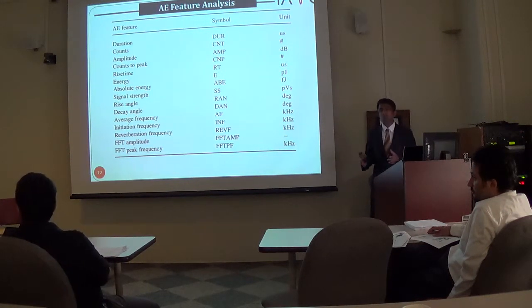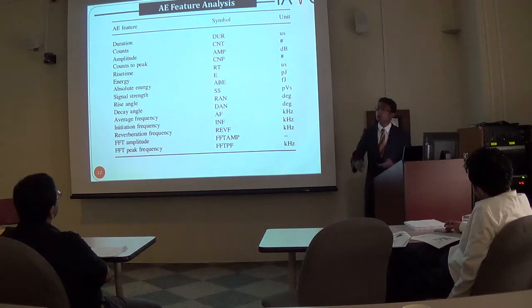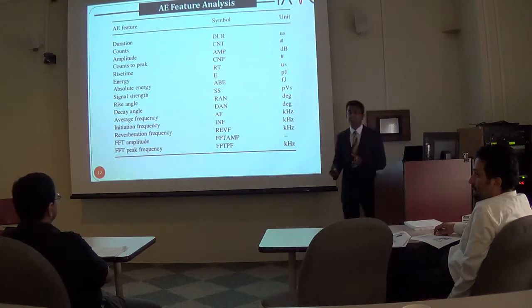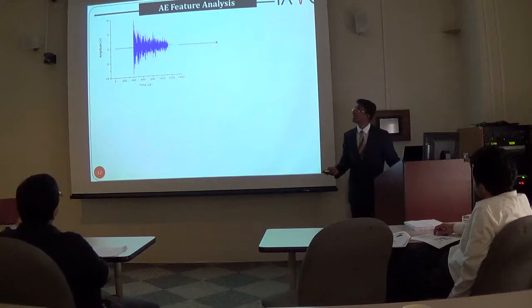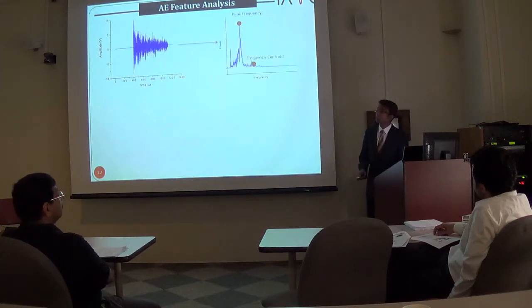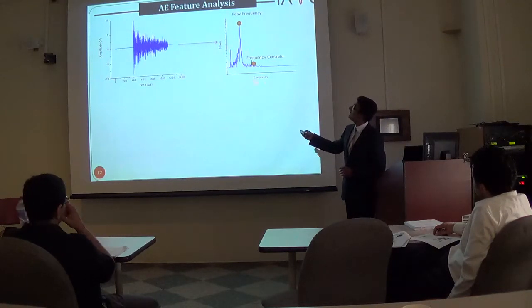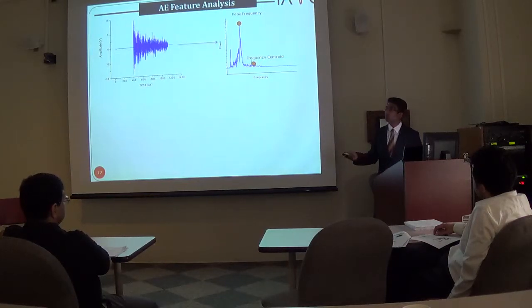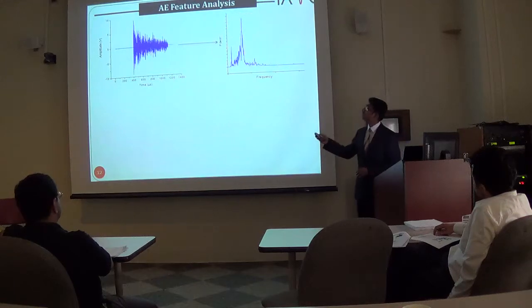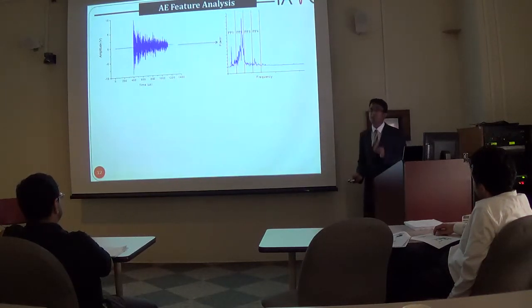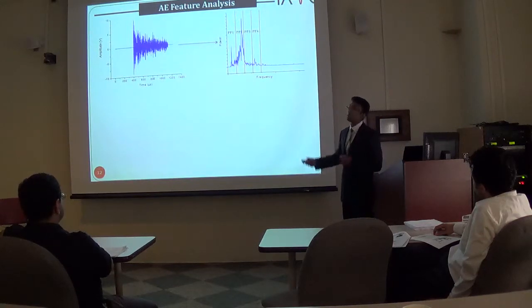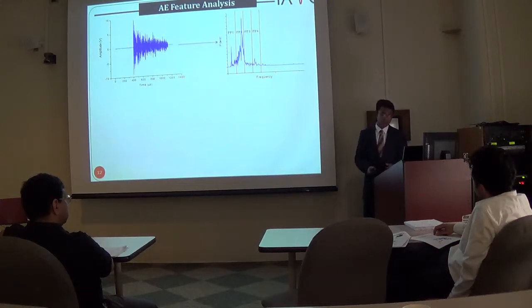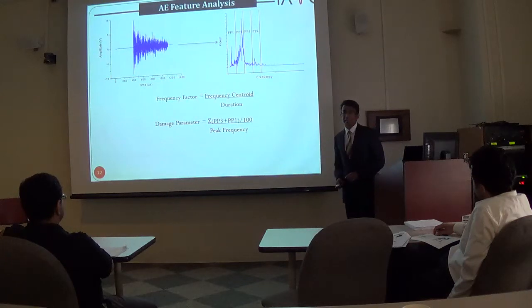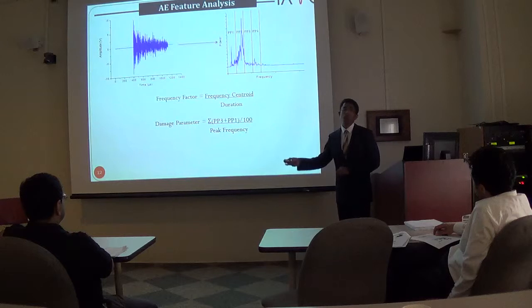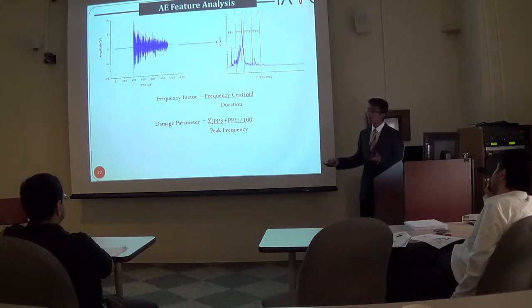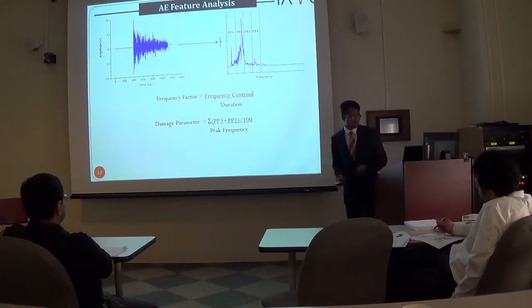However, in our research, I wanted to go a few steps further and develop both novel AE descriptors and also advanced AE feature descriptors that are reliable for damage detection. For that purpose, the AE waveforms extracted during the test were comprehensively analyzed and shifted to the frequency domain using FFT algorithms. In addition to picking up the peak frequency, other advanced frequency analysis was also performed to identify the frequency centroid. Further, the FFT spectra were dissected carefully into 4 specific spectral ranges, and the percentage of energy in each of these spectral ranges was then calculated and seen to be correlated with the applied loading conditions. Consequently, based on these advanced AE analyses, novel AE feature descriptors were designed based on the relationship of these features and also the relation of these features to the conventional AE features. These are 2 of the common AE feature descriptors that I've designed, in addition to a few more.